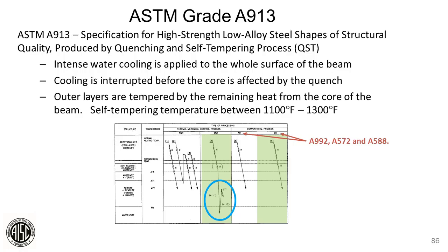And this was one of the grades that Shane talked about, A913. We've talked about before what the controlled rolling does for us. Here's a case though where the A913 grade is where we're cooling it after it's done rolling; it'll be quenched and self-tempered. The typical A992, 572, and A588 would either be as rolled or control rolled. In the case of heavy structurals, the vast majority is going to be control rolled, because in bleeding the heat off and trying to hit Charpy properties, you just about need some sort of controlled rolling in place. If you look at the squiggly lines on the control rolled, you'll see where the bar is being rolled, then you'll see the pause that we saw on that graph earlier, and then you'll see rolling continue again.